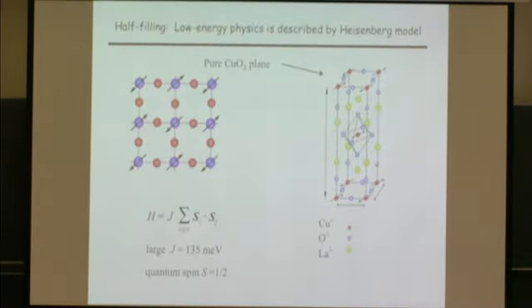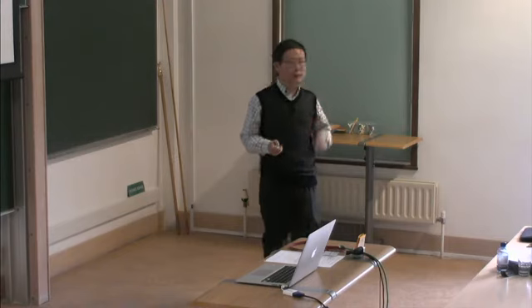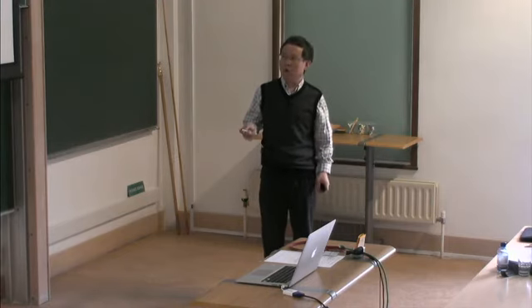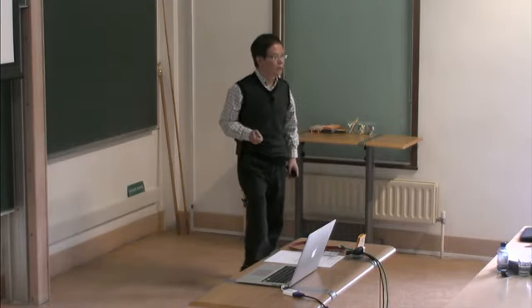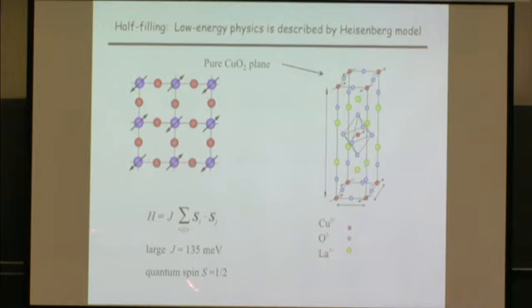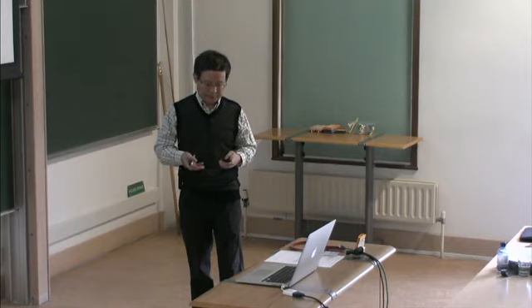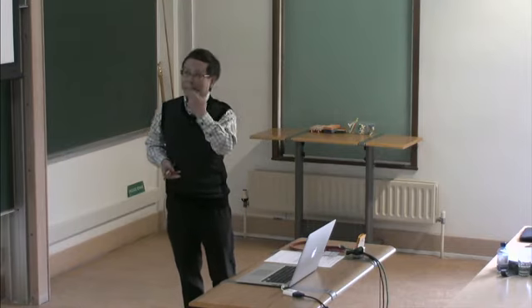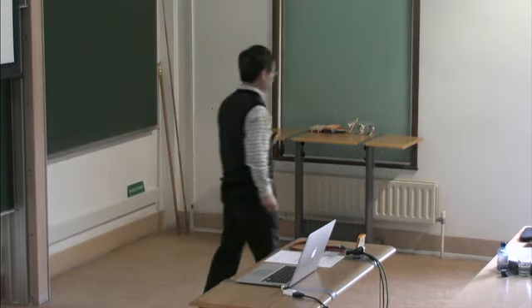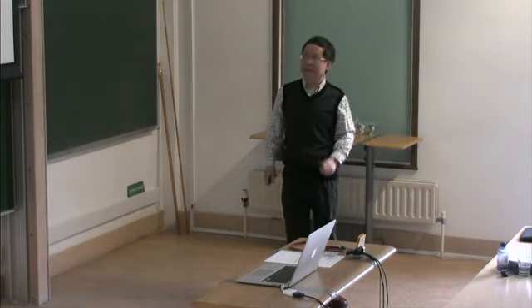At the half filling limit without holes, this model reduces to the Heisenberg model, which actually fits with experiment very well. So it has been well established. The Heisenberg model actually describes the cuprates at half filling, the low energy physics, quite well. This is firmly established, and so the challenge will be how you dope this system.